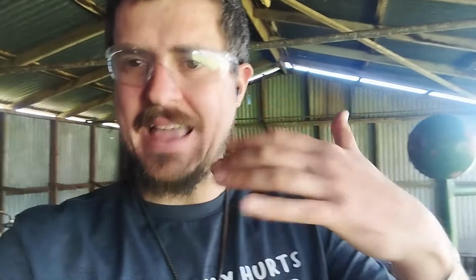forge weld with, because there's still a lot of slag inclusions in this steel, and you can kind of see it as the blackening spots. They cool much faster than the iron does. So we need to kind of push through that to get the iron pieces to stick together, and it's probably going to be a dirty weld. It's just how it goes. That's why we're doing multiple, because each one's going to squeeze out more of the slag. But by doing that, it's going to probably want to spray everywhere.